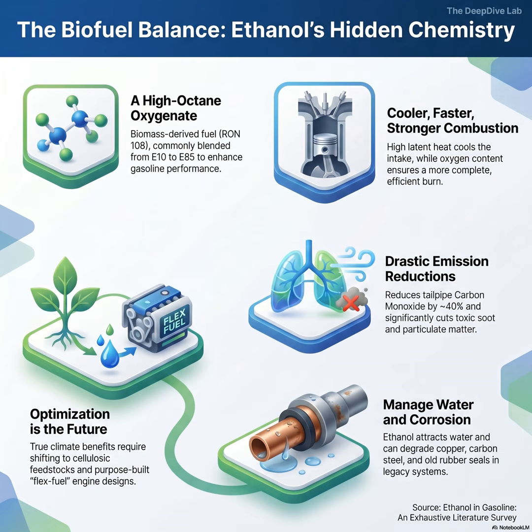The plastic swells, losing its tensile strength and becoming dangerously soft. That sounds like a disaster waiting to happen. It is, but the true catastrophic failure happens when the fuel system dries out. Ethanol is a powerful solvent. When it evaporates, it doesn't leave empty-handed. Wait, what does it take with it? It extracts the plasticizers. Those are the specific chemicals engineered into the plastic to keep it flexible. So when the part dries, it shrinks significantly below its original size. It becomes rigid, brittle, and fractures under pressure. Suddenly, your high-pressure fuel line is leaking.